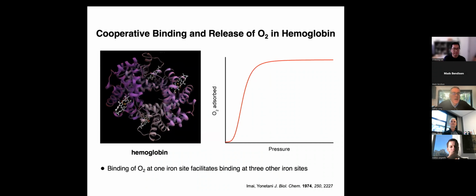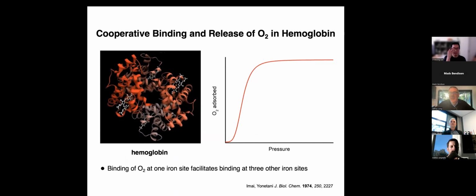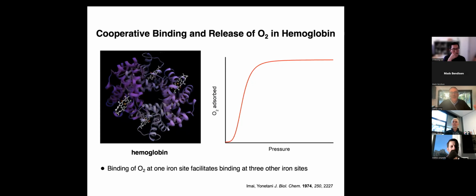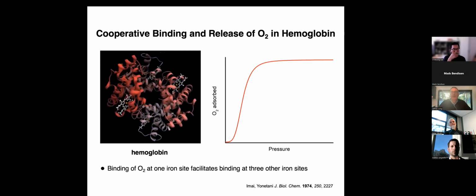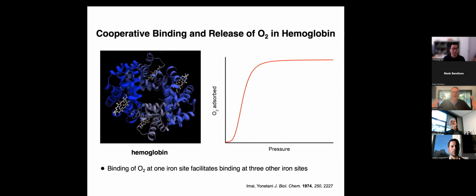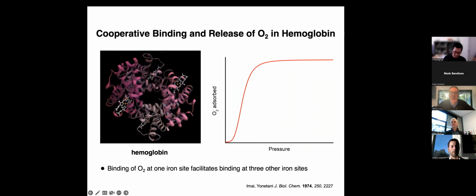captures oxygen. So most chemists are familiar with hemoglobin, but here you've got 4 iron heme sites, and when oxygen selectively binds at one of those iron sites, it triggers a rearrangement of the protein backbone and opens up access to the other 3 iron hemes for oxygen binding. And so hemoglobin essentially has a breathing sort of mechanism where it will simultaneously bind or release 4 oxygen molecules at once. And so the adsorption isotherm that you get is shown at the right. You see a step instead of that Langmuir shape. And this allows hemoglobin to either fully unload or fully load with oxygen in a very narrow concentration window.